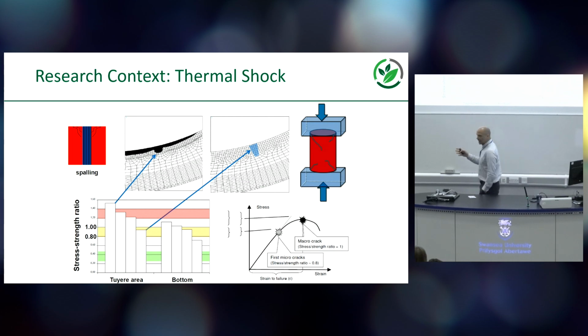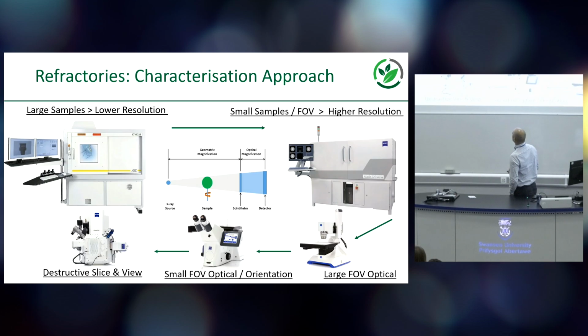So we've got to balance that against the thermal, and the one way we do that is by putting more carbon in. So ironically, the more carbon that you put in, the worse the thermal efficiency, but the better the thermal shock resistance, so you get something that's more durable, but less thermally efficient. And so those two things have to trade off on one another if you look at them in an isolated fashion, which we're not going to do.